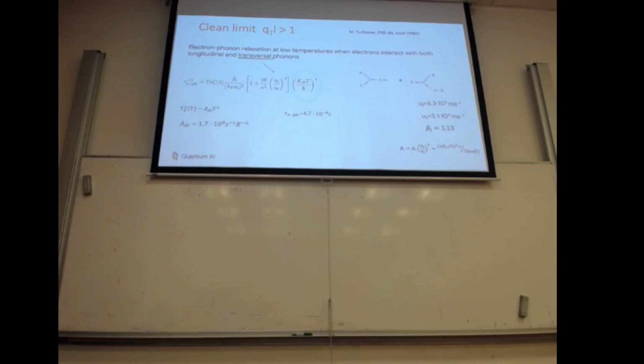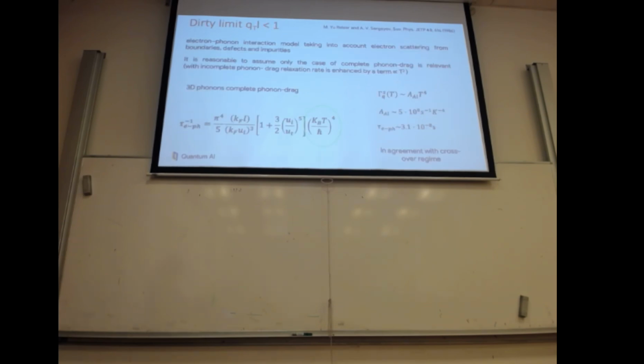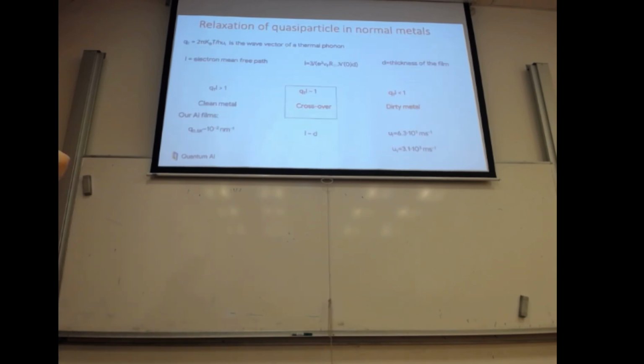And what he sees is basically that there should be a temperature dependence of this relaxation time that goes with T cube. So basically, if you take aluminium, what you would expect from this theory is a relaxation time of the order of 4.7 times 10 to minus 8. And so they are surely shorter than the estimate of Kaplan. So we have T cube for clean.